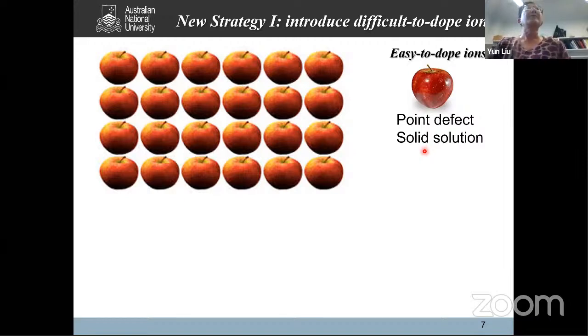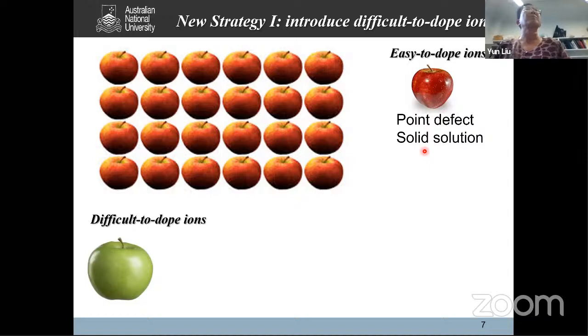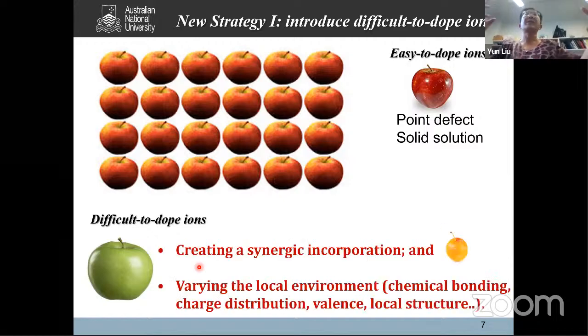On the other hand, that's our new strategy. We try to introduce some extrinsic, what we call difficult-to-dope ions, such as lithium in the barium titanate. They are quite different in comparison to the ions in the host material. In that case, we can use another atom to create a synergic incorporation. These two extrinsic ions will correlate with each other to form a very unique defect cluster. That will create a different opportunity. These difficult-to-dope ions alone cannot stay. They have to push the surrounding chemical environment to change quite significantly to stay in this structure.